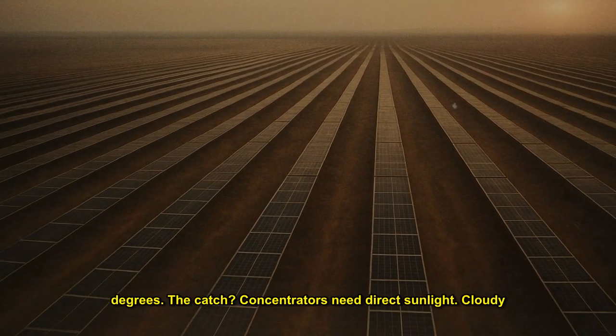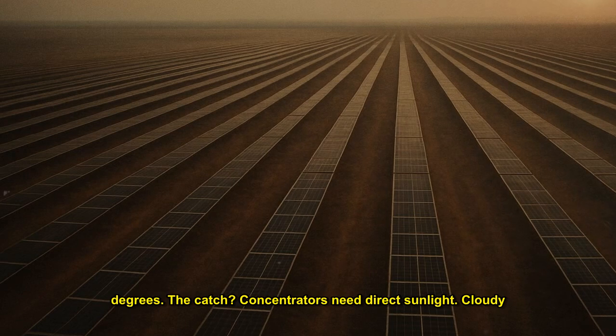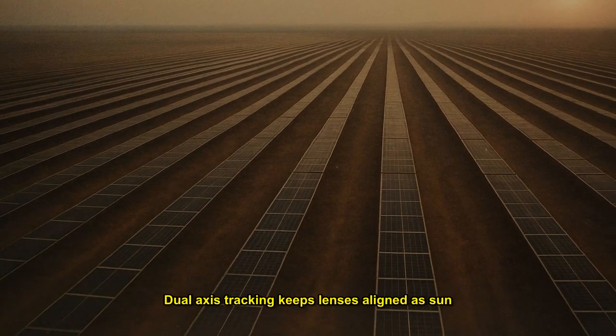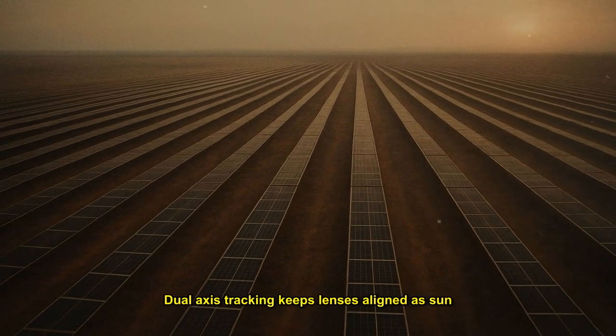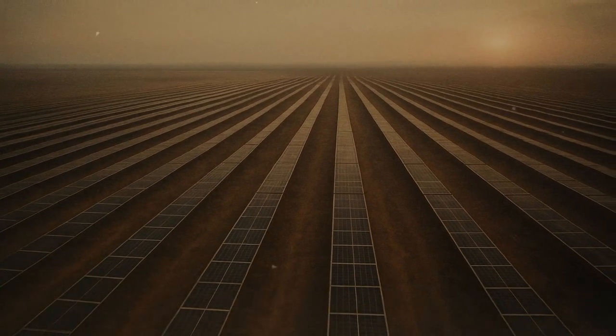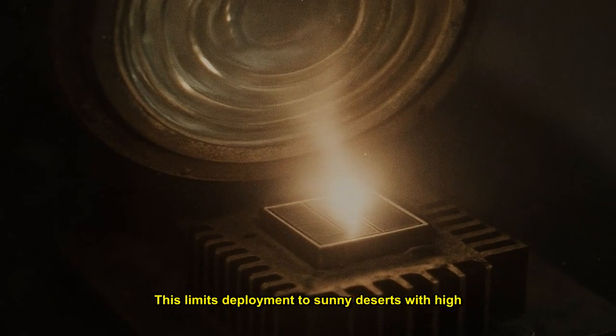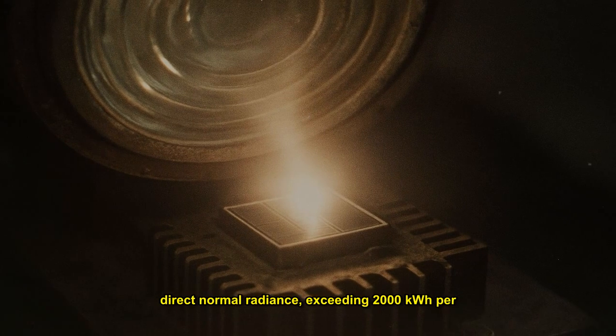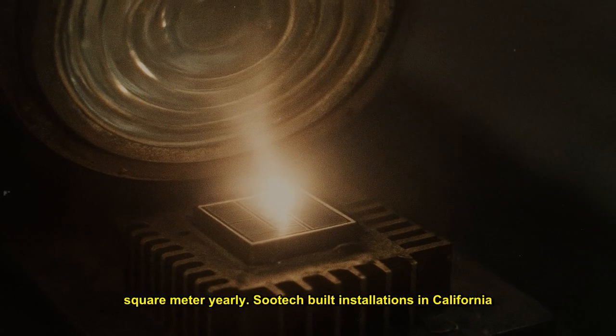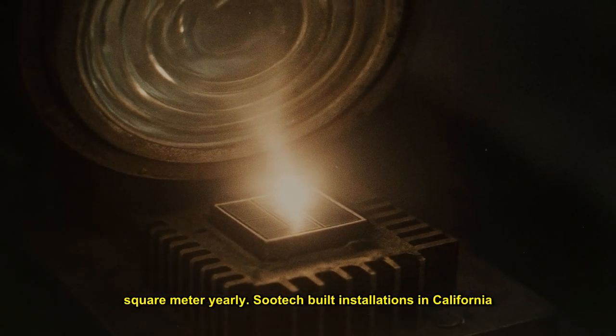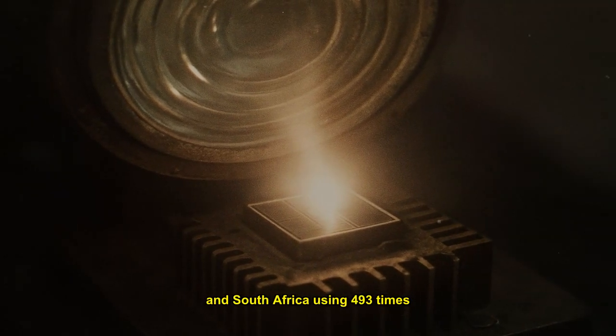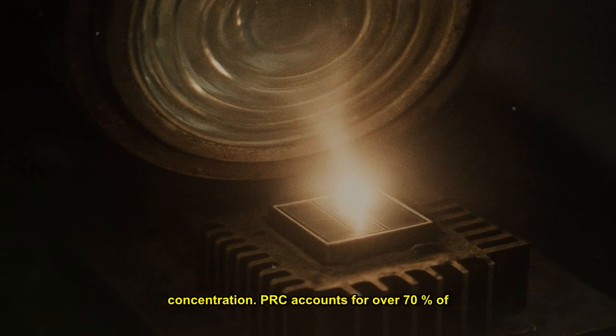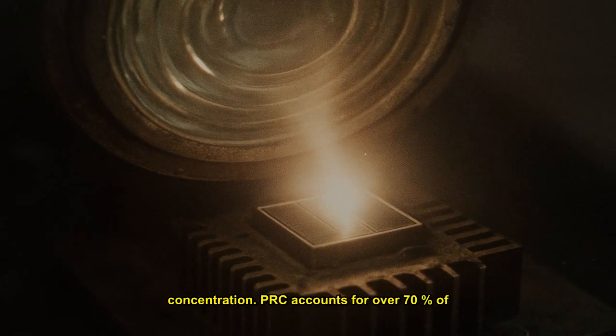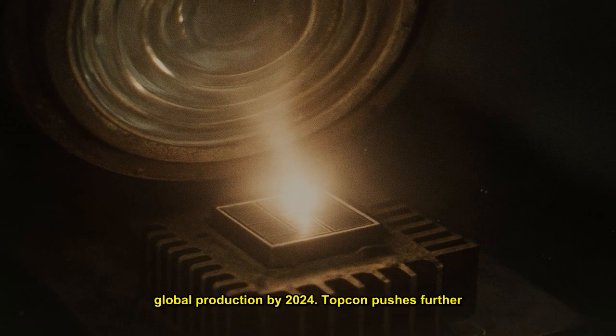The catch? Concentrators need direct sunlight. Cloudy days produce nothing. Dual axis tracking keeps lenses aligned as the sun moves 15 degrees per hour. This limits deployment to sunny deserts with high direct normal irradiance, exceeding 2,000 kilowatt hours per square meter yearly. Soitec built installations in California and South Africa using 493 times concentration. PERC accounts for over 70% of global production by 2024.